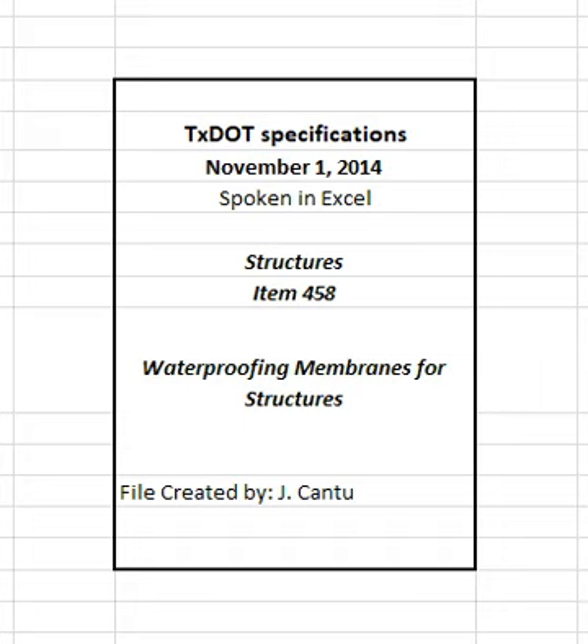Turn the membrane into drainage holes and castings without break. Take special care to make the waterproofing effective along the sides and ends of members to be waterproofed. Install the butyl rubber membrane by first applying the adhesive as recommended by the membrane manufacturer. Apply the adhesive to the surface to be waterproofed and at necessary splices, in a solid area extending approximately 36 inches back from the edges. Apply the membrane by pressing it firmly and uniformly in place against the previously applied adhesive, avoiding wrinkles and buckles. Make splices, laps, and flashing in accordance with the membrane manufacturer's recommended procedures.